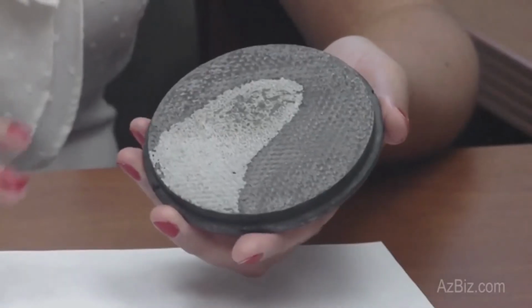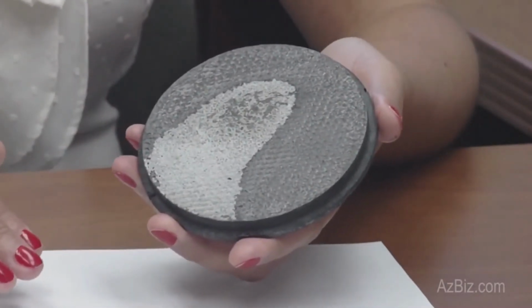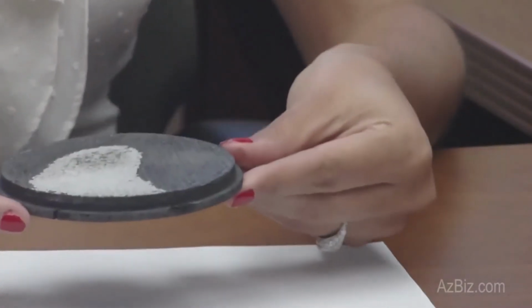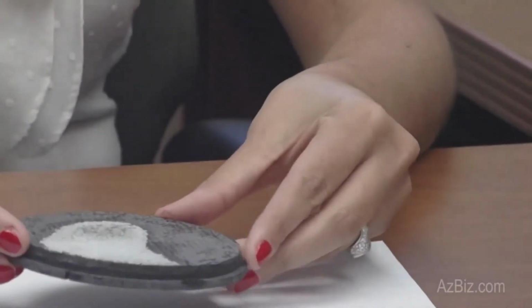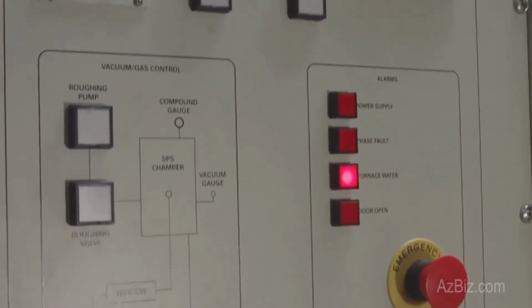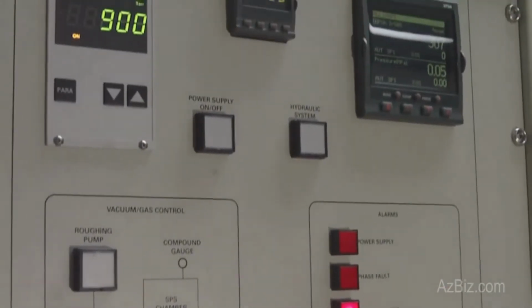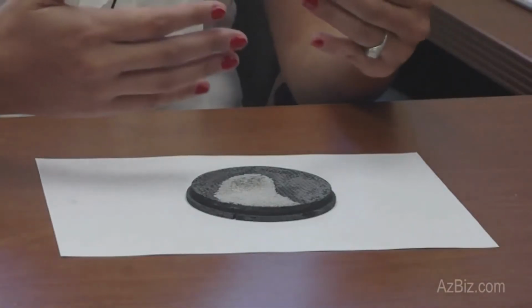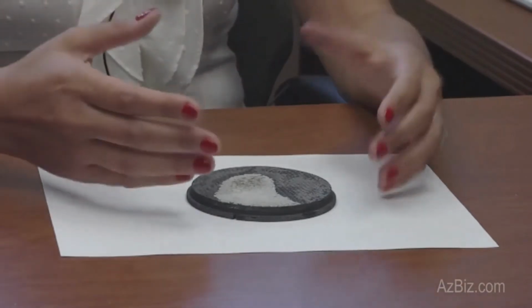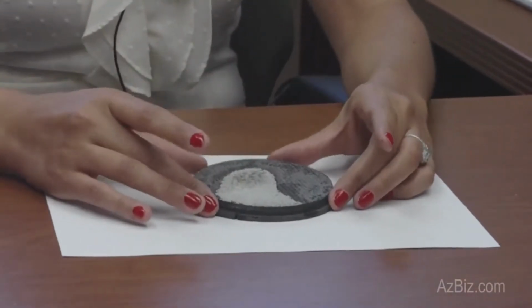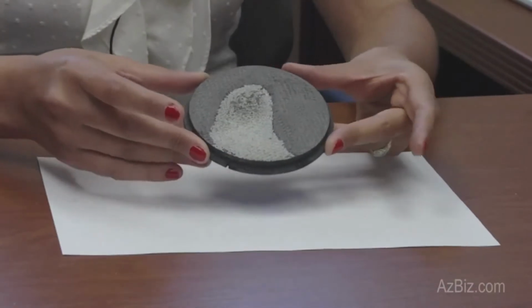Engineering high-temperature materials. In particular, we work with ultra-high-temperature ceramics, composites, and coatings. These were very early preliminary results, and we have other samples that have shown even better oxidation protection for the carbon-carbon substrate that we're currently working on. We're going to be testing at the National Solar Thermal Test Facility at Sandia Labs. For me, as an outside researcher in a non-government lab, this test sample would cost me more than $40,000 to test.